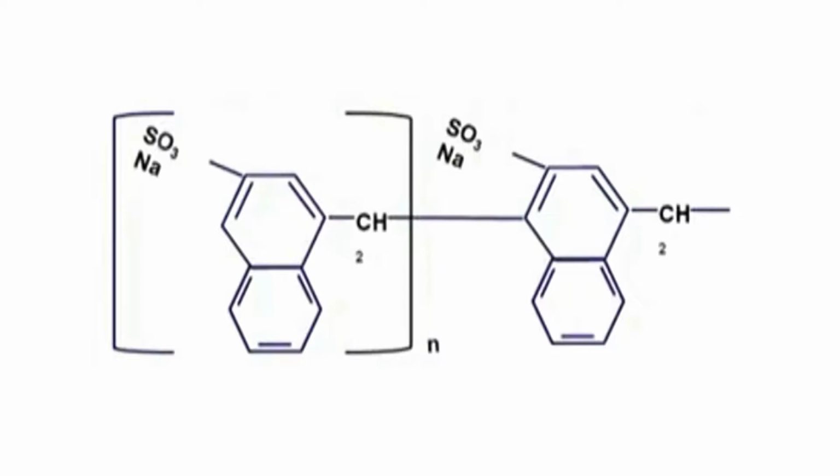The sulfonated naphthalene formaldehyde is obtained by sulfonating either petroleum or tar at high temperature. The SNF, sulfonated naphthalene formaldehyde structure is being shown. The molecular weight of SNF is 500 to 2500. Compared to plasticizers, its molecular weight is less, and this paves the way for better dispersion since more particles get absorbed to the cement surface.